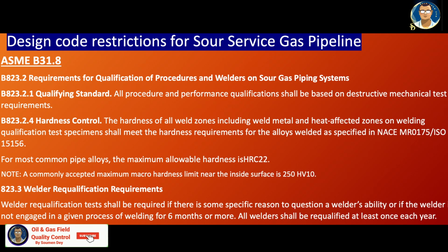Generally, we qualify the welder only on the basis of radiographic testing. On their test coupon we do radiography if it is non-sour service, and if radiography passes, the welder is passed. But in this case, we need to qualify them with bend test and tensile test as required in the qualification code. Hardness control: the hardness of all the weld zones, including weld metal and heat affected zone on welding qualification test specimens, shall meet the hardness requirements for the alloys welded as specified in NACE MR0175 or ISO 15156.